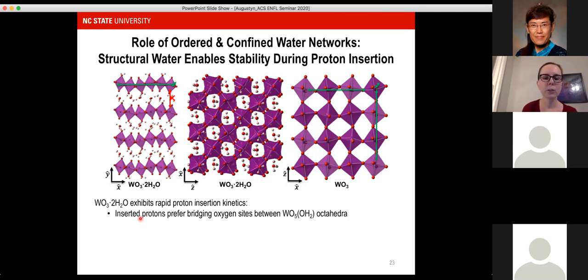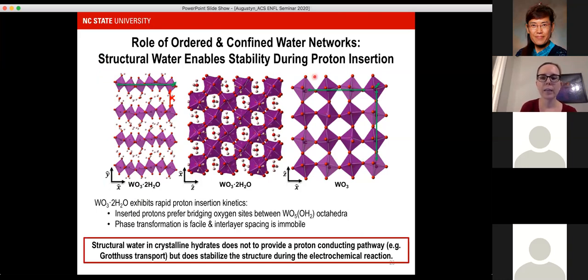We know that the inserted protons prefer the bridging oxygen sites. So those sites are located here, or if you're looking top down on the material, they're located here. The phase transformation is very, very quick in this material, and there's no change measured in the interlayer spacing, this dimension here. This water layer appears to be hydrogen bonded, very stable. Whereas for the anhydrous material, because you have these interconnected octahedra, we think there are too many degrees of freedom, if you will, for structural transformation.